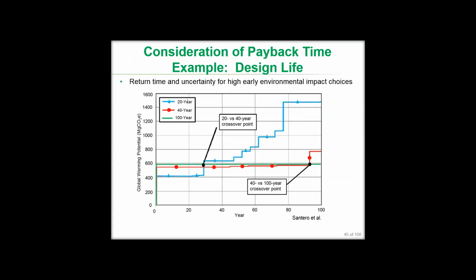I actually scrambled back and found the original paper to remind myself from about 10 years ago. So the way this was done, of course these are simulations, the 20-year design life is about an 8-inch concrete slab. The 40-year design life was about a 12-inch concrete slab. And the way these maintenance and rehabilitation scenarios were put together was using MEPDG to estimate the cracking, and then applying CPR based on the cracking levels until we reached the level at which the Caltrans maintenance and rehab guidelines would indicate that we needed to go to an asphalt crack seat and overlay. And then from that point forward, you're updating that asphalt overlay.